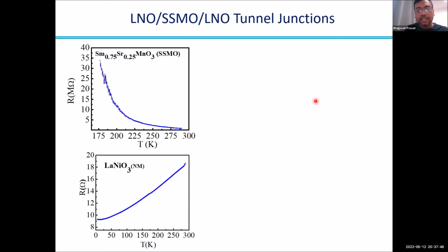So let's now see the transport data. This is the R versus T of the SSMO films. What you see is insulating nature. We measured these devices all the way down to 5 Kelvin, but it's so insulating that below 175 K we could not measure it. I did measure all the way down to 5 Kelvin to make sure that no metal to insulator transition is happening at low temperature.